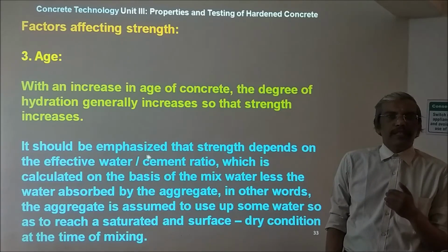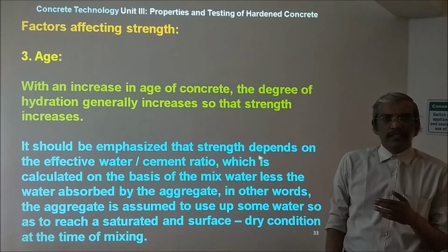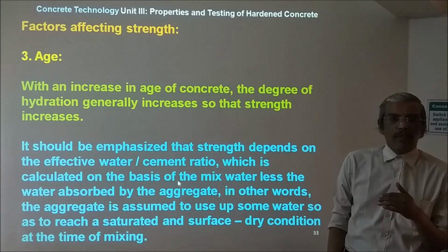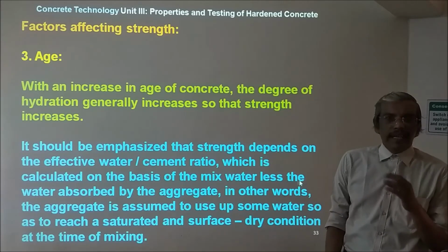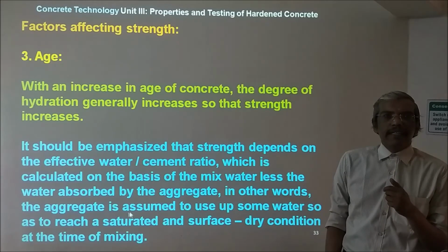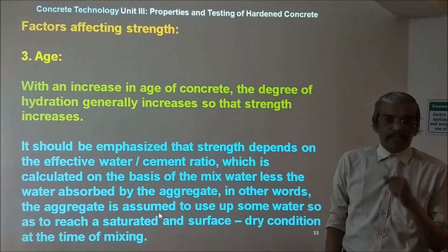It should be emphasized that strength of the concrete depends on the effective water cement ratio, which is calculated on the basis of mixed water less the water absorbed by the aggregates. In other words, the aggregate is assumed to absorb some water so as to reach a saturated and surface dry condition at the time of mixing.